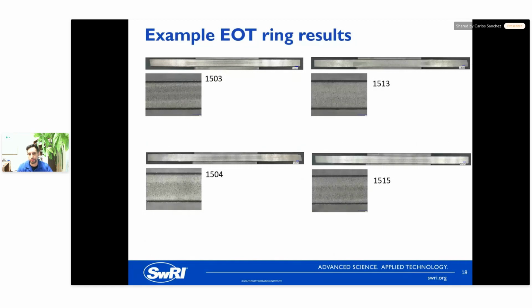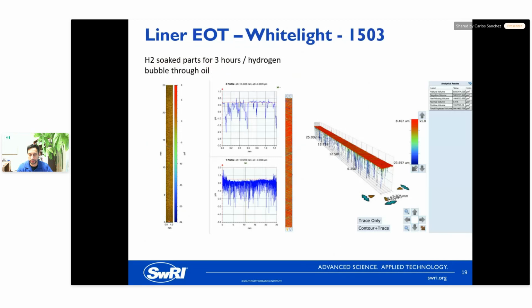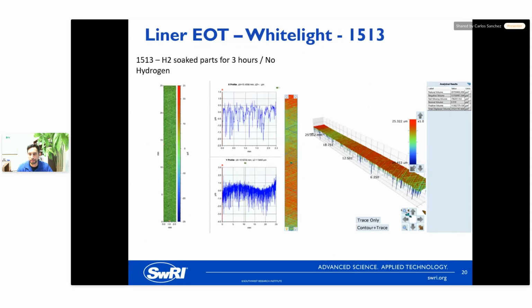Those are the ones that were the more severe hydrogen case on the right. And then we also did some measurements looking at white light interferometry to see if there's any more severe cases. So here is hydrogen being soaked for 3 hours, and this case bubbled through the oil. There's a little more dip on the reversal points, a little more wear on that side than the parts that were soaked for 3 hours with no hydrogen running through the test itself.